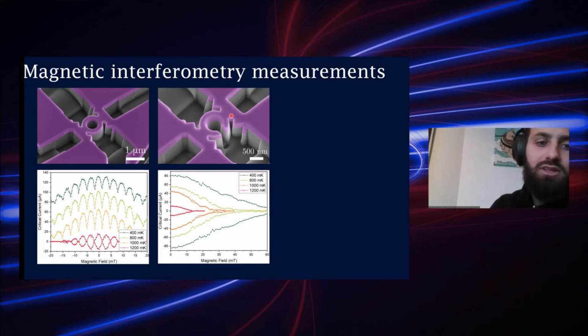Whereas for strontium ruthenate, there is not so much variation. I would say mostly you find flakes between 200 nanometers and 1 micron thick—these are the thicknesses that pop up the most.